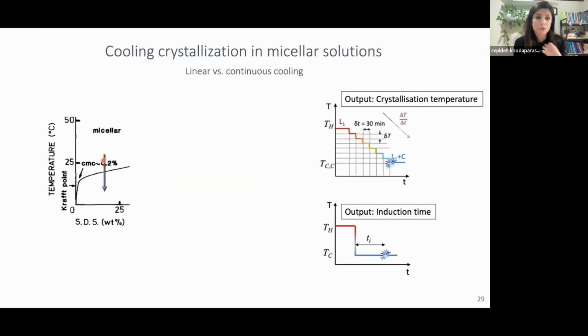So to be able to measure this temperature, what we typically do is either we slowly cool down our solution and detect the first temperature at which the crystallization occurs, or we cool down the solution to fixed temperatures and wait there until crystallization happens. The question is, how do we cool down the solution? How fast or slow do we cool down the solution? And if we go down in temperature and wait, how long do we wait?